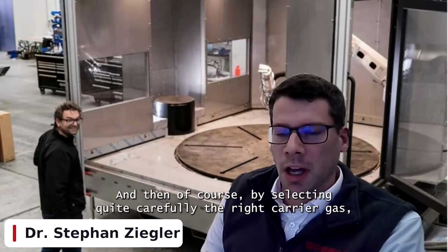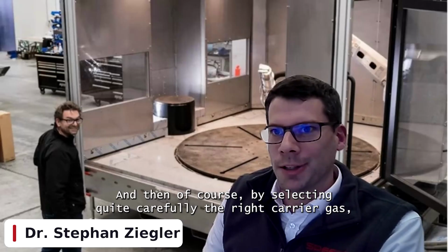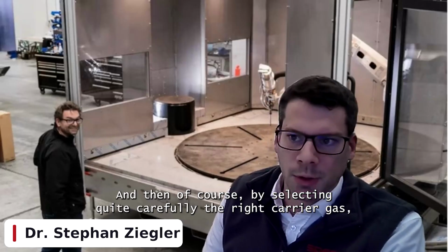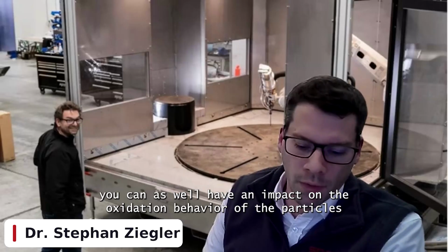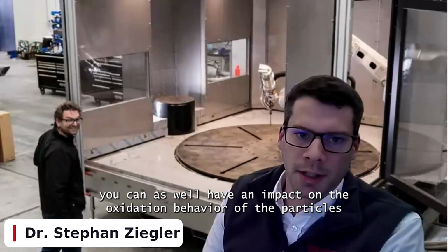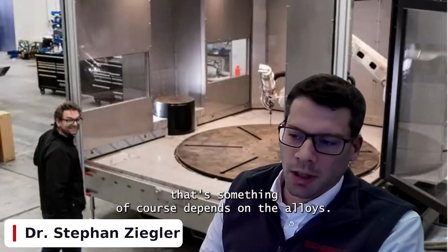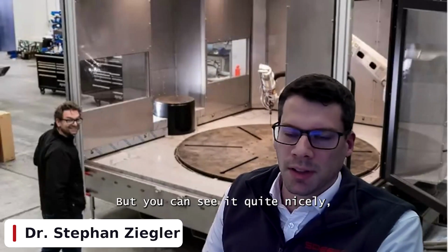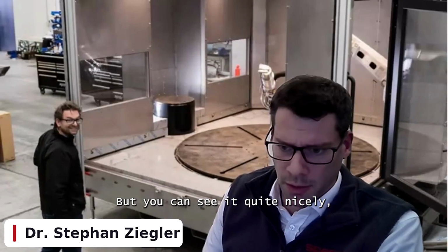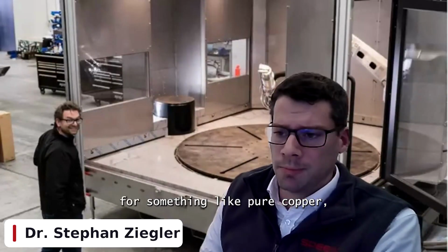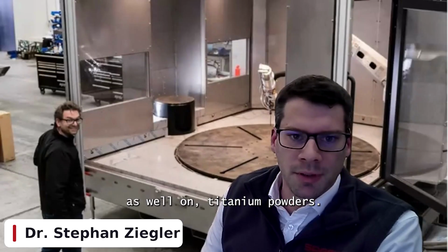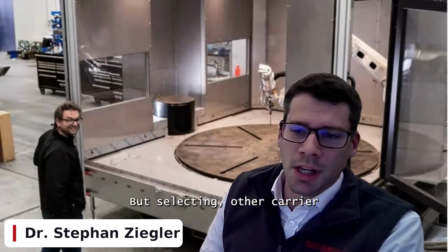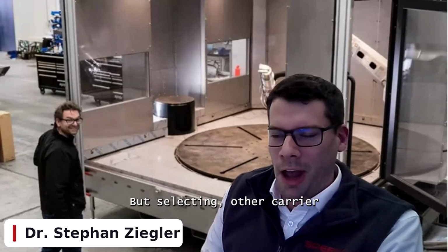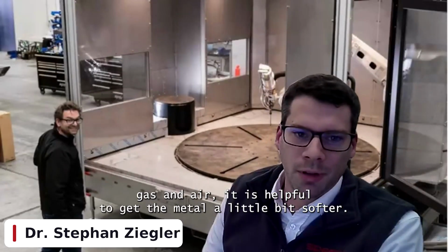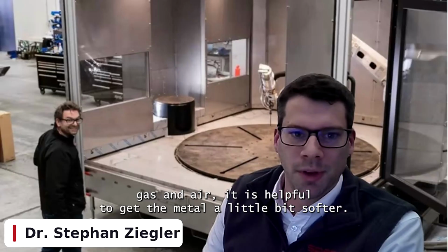And then, of course, by selecting quite carefully the right carrier gas, you can as well have an impact on the oxidation behavior of the particles within the process itself. That's something, of course, that depends on the alloys, but you can see it quite nicely on, for example, pure copper or as well on titanium powders. But selecting other carrier gas than air is helpful to get the metal a little bit softer, for example.